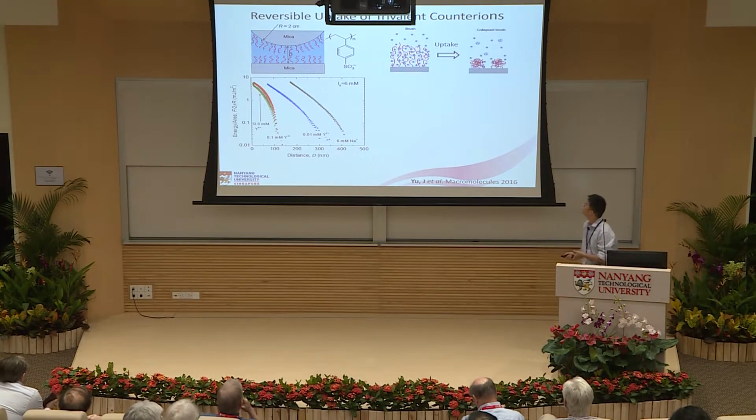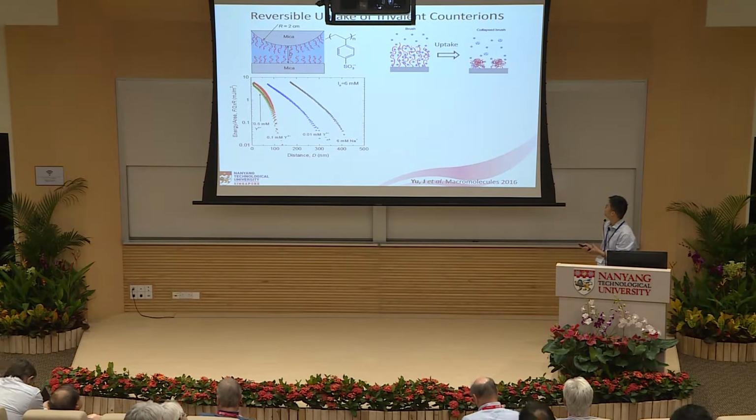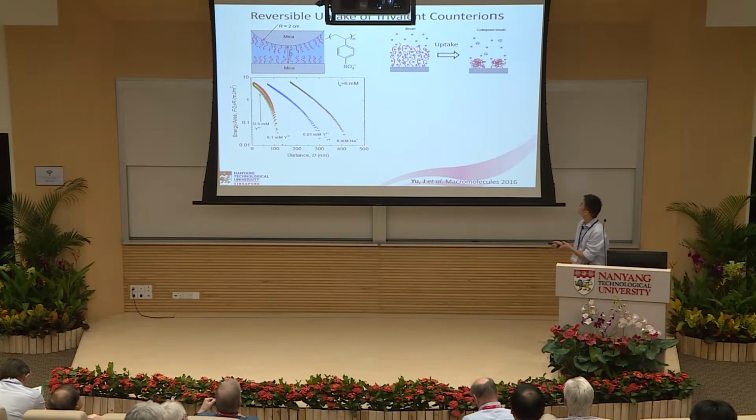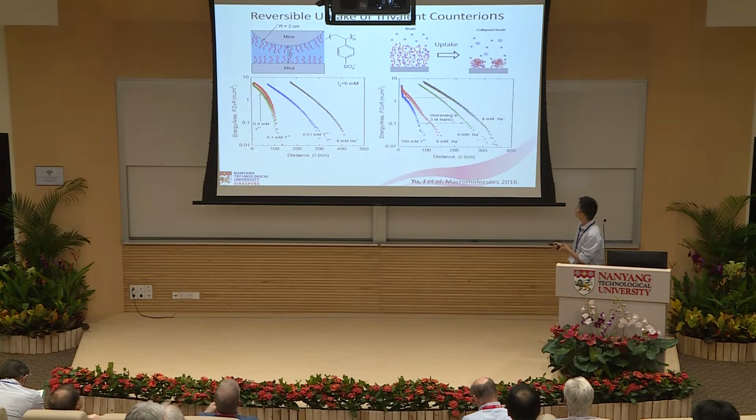Based on that, we believe the trivalent ions replace the monovalent counterions in the solution, which causes the collapse of the brushes, as Professor Matthias talked about on Monday.